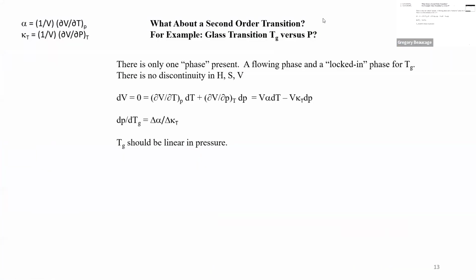So if you take that same Clausius-Clapeyron approach, when you have a glass transition, there's no change in state really. If you take an X-ray diffraction of a liquid and then of the glass, below the glass transition and above, the X-ray diffraction pattern is exactly the same. The stuff is the same. So it's really basically a topological transition.